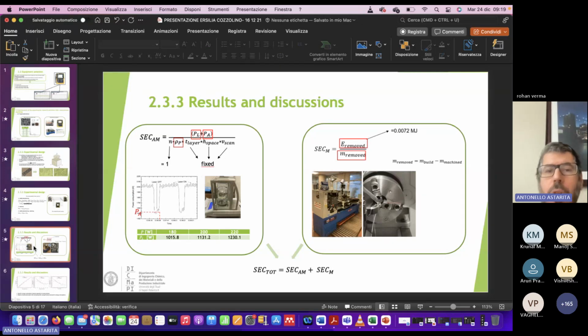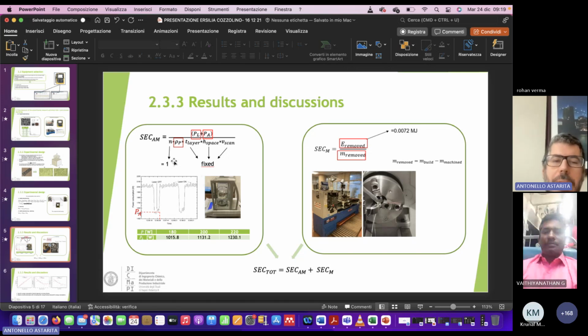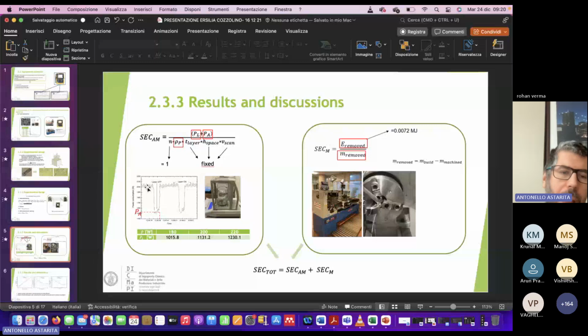In our activity, we measured both the quantities. So in this formula, we don't have the theoretical calculation, but we have the actual calculation, because we performed experiments and we measured the energy consumption. For instance, you can see during the production period, you have the period in which the laser is working, you have a very high power consumption, but then you have the period in which the laser is shut down, in which the power consumption drops. You have the first layer, then the laser operates, then you have the second layer, then the laser operates, and so on. So during the process, you have some time in which the laser is operating and some other time in which the laser is not operating.